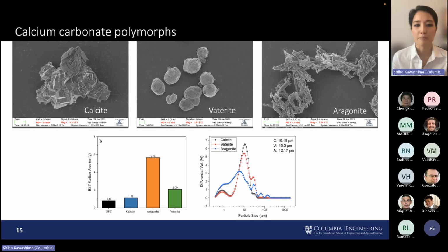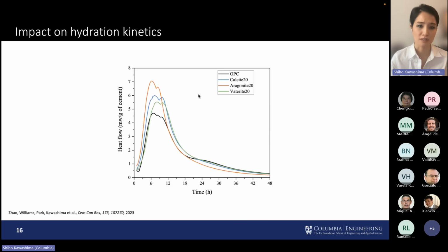So I mentioned that by adjusting the parameters of this process, you can form different polymorphs. So these are all calcium carbonate. And in nature, calcite is what we typically see. So the limestone filler that we use in construction, that's all calcite. And the reason is because that's the most stable form of calcium carbonate. But then there are also other forms, metastable forms, vaterite and aragonite, which are rarely seen in nature. I think aragonite is seen very limitedly in nature. Vaterite pretty much not at all, as far as I understand.